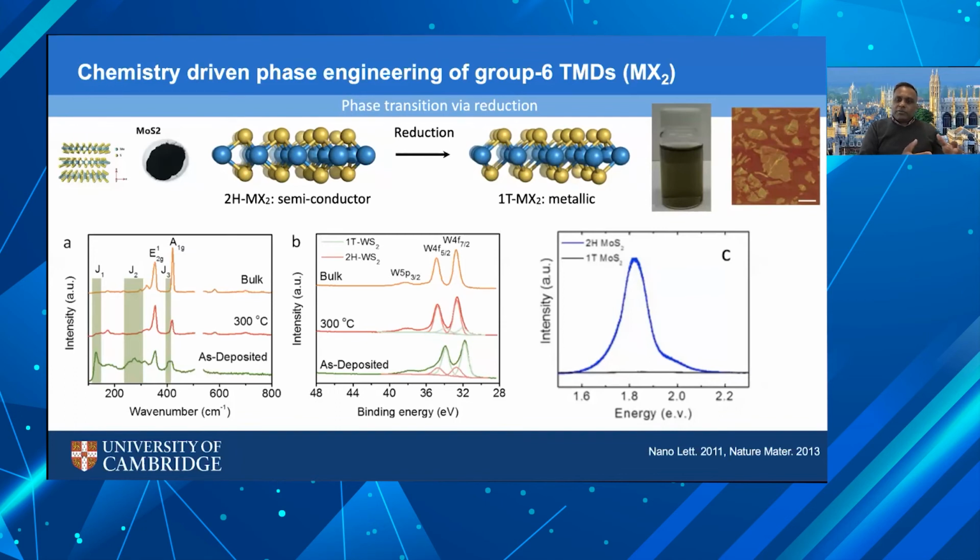So I think that's the main challenge with working with metallic materials. In one way, counter to that, one reason why these metallic phases are so useful is that in these kinds of electrochemistry applications, what you really require is something that is highly conducting, highly metallic, but non-reactive, right? That's why platinum is such a good catalyst. So if you have something like MoS2 or a sulfide that is highly conducting, but non-reactive, because it's a single layer with passivated electrons, it's quite reasonable that these materials would work in the kinds of applications